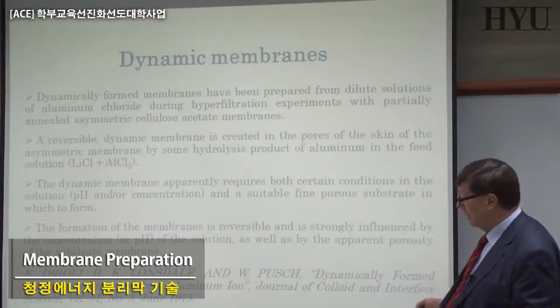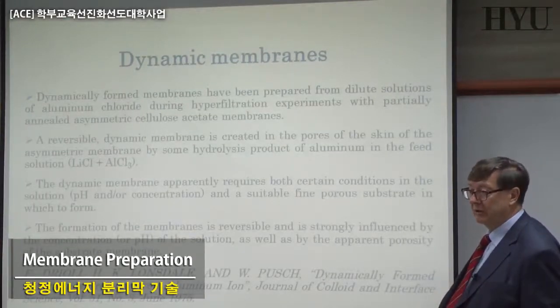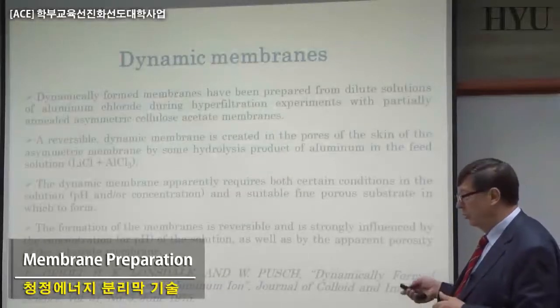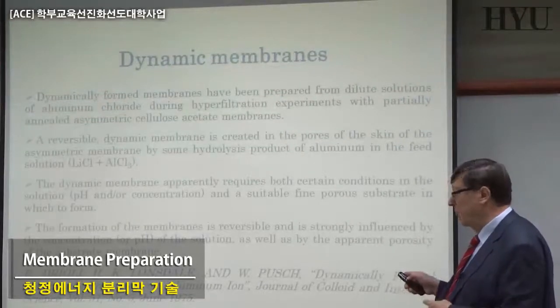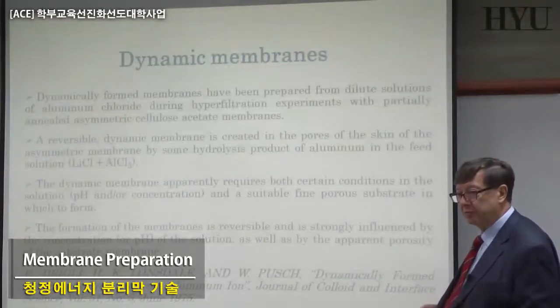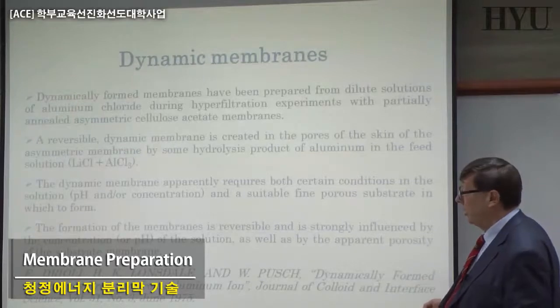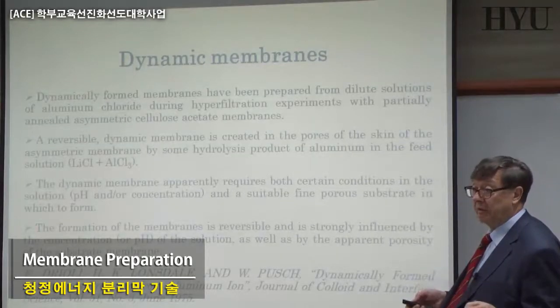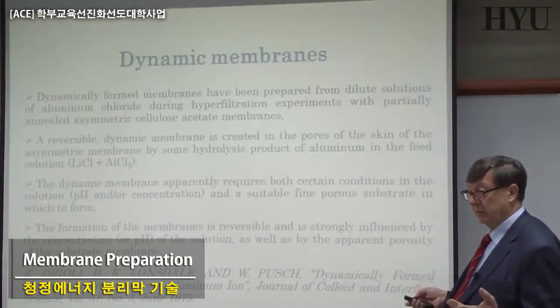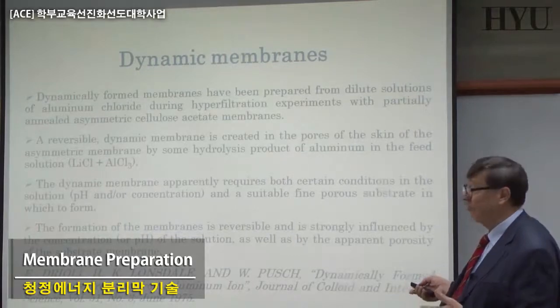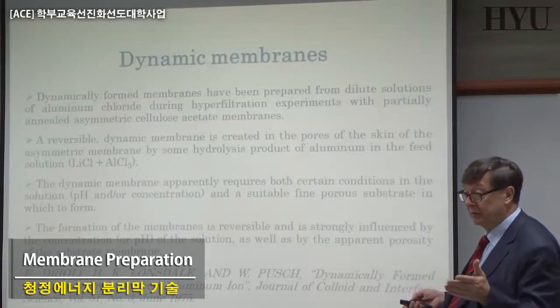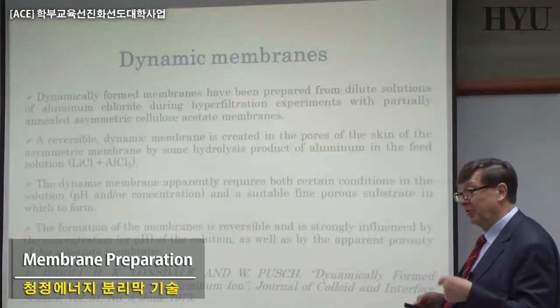The reason was that they had a very nice tube, carbon tube, stable at high temperature. Textile industry discharge is at 80 degrees centigrade, 85, not easy to use normal ultrafiltration. This dynamically formed membrane was stable with the temperature. And that became a system. Today, more and more, this can be present in bioreactors. In bioreactors, you can form a gel of your enzyme, and people are using more and more the same concept.